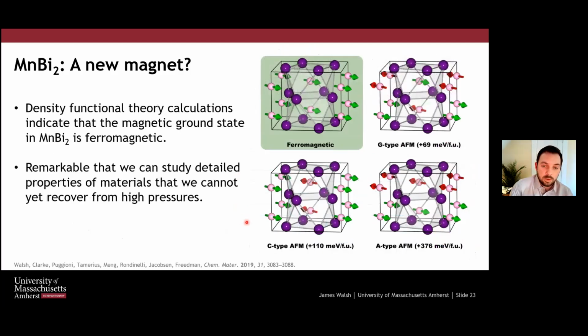But the nice thing about modern computational chemistry being what it is is that we can still investigate this phase. Even though we can't really recover it and do the bulk measurements that I described for copper bismuth, we can still use density functional theory to get an idea of whether it's a permanent magnet. These calculations were carried out by our collaborators at Northwestern at the time, the Rondinelli group. It was Danilo who actually did this work. What we can see is that the ferromagnetic configuration has a lower energy than the rest. As long as we've tried every possible, in this case, Ising configuration of the spins, we should be able to compare and rank by energy and see which magnetic state is the ground state. It indicates that we have a ferromagnetic ground state. So manganese bismuth 2 presumably is a new ferromagnet and perhaps a permanent magnet.